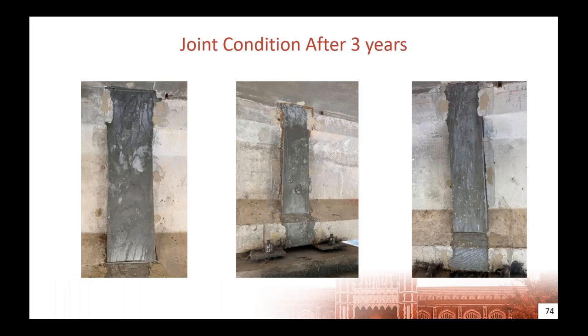And these are those very same joints after 3 years, which we just recently took pictures of. They look more or less the same, with slight lighting differences. No additional damage appears to be caused by environmental conditions. UHPC, because of its very, very low permeability, tends to resist a lot of the traditional attacks that most concretes are susceptible to. So it seems to be performing really well after 3 years. We were able to maintain restored continuity with the new UHPC joint.